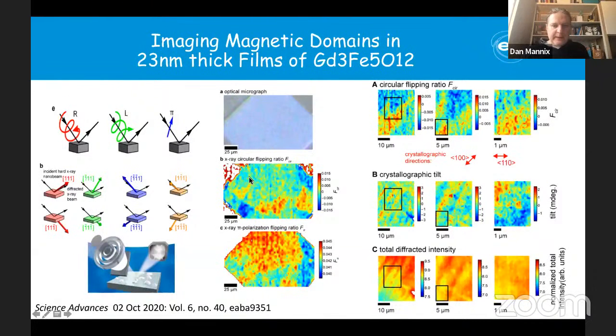The second aspect that I referred to in the beginning is looking at the difference between pi and linear polarization incident on the sample. This again is the circular polarized light, where we can see these images of magnetic domains, both high and low, red and blue. What we can also see is a large region here which is basically zero. One possibility could be that this area is related to domains which are out of the scattering plane and therefore only very weakly picked up in this contrast map. So if we come in with the pi light, we actually pick out a domain in this large area region, which agrees with that scenario that this region would be domains out of the scattering plane.